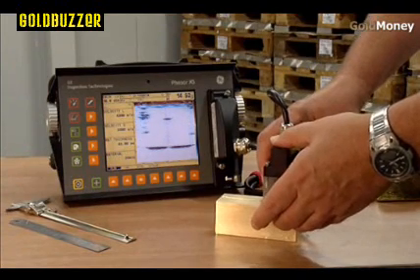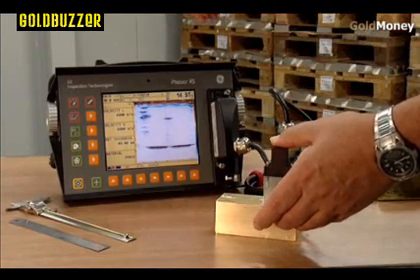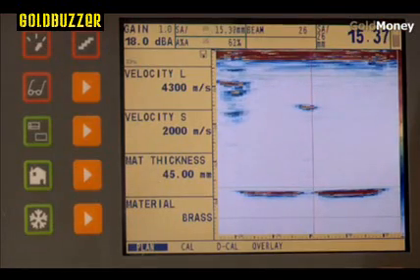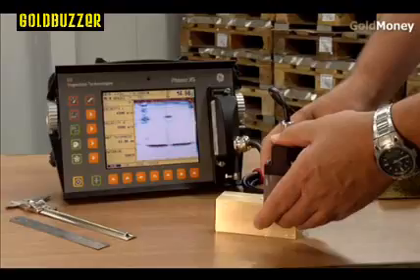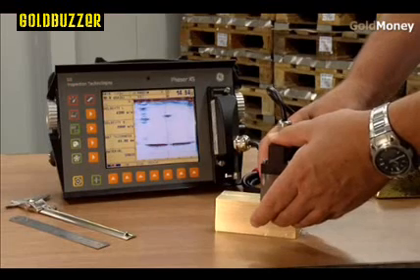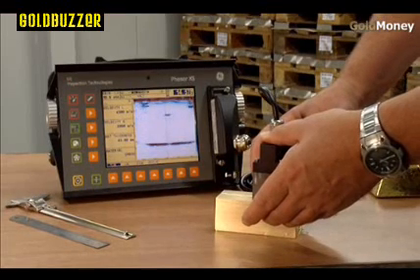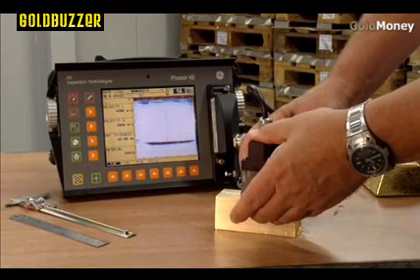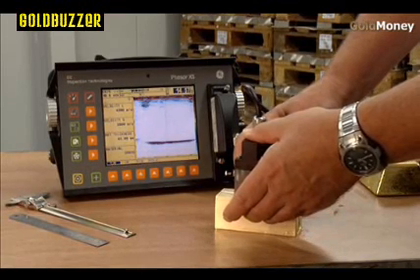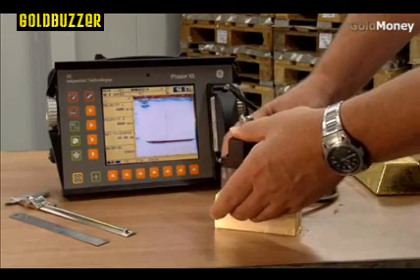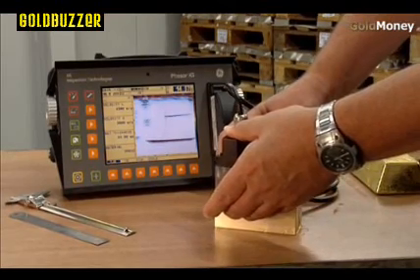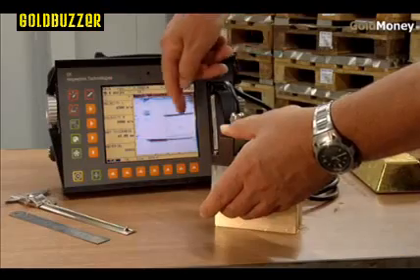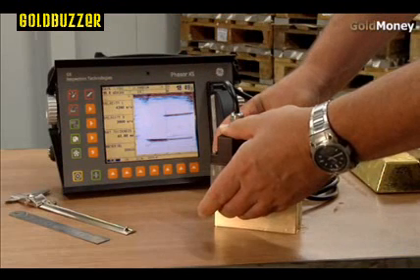On this image we can clearly see that we now have a defect showing — top of the material, back of the material. That's the indication of a defect, and that's how a defect would look in a gold bar. We've now moved off the defect and carry on scanning across the surface. Now we've got a much larger defect showing — that's a signal from the larger defect.